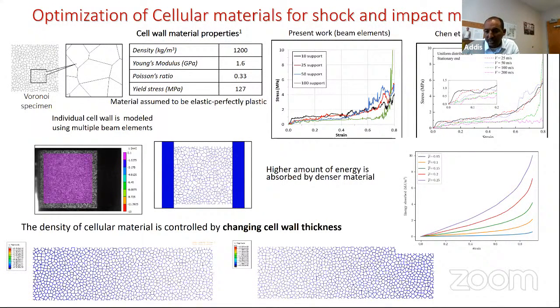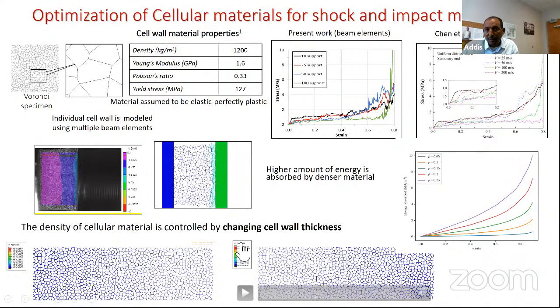The reason we say that is it's well documented that the response of this material highly depends on the density of the parent materials as well as the relative density. So having said this, if we can optimize the way these cellular materials are arranged in one material system, especially in the case of high strain loading, we can increase the energy absorbed in these materials. So using our finite element models and digital image correlation, we first try to match how the material responds for homogeneous materials and then start using graded material systems.